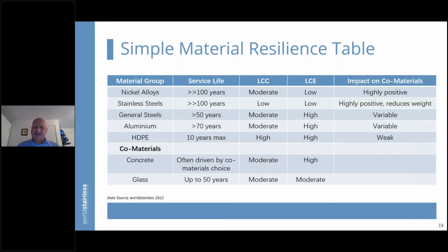At the top of that list, you've got, and you wouldn't be surprised by this, nickel alloys, stainless steels. They have long service lives. There's a slight difference in life cycle costing. Stainless steels do tend to be much lower. Life cycle emissions, they're both low because they don't need the interventions. General steels will have a shorter but respectable service life with reasonable life cycle cost, but suffer on the emission side, as does aluminium. And then high density polyethylene at the bottom is not going to last terribly long.